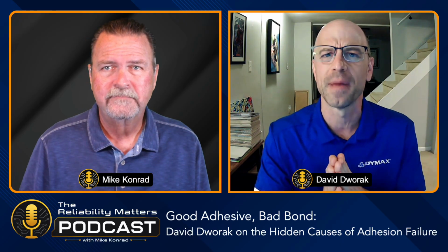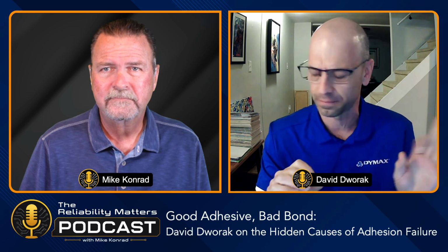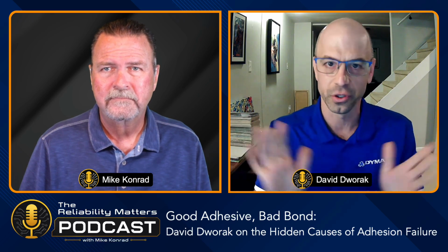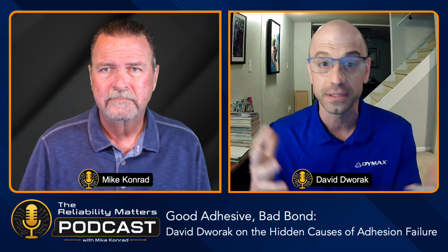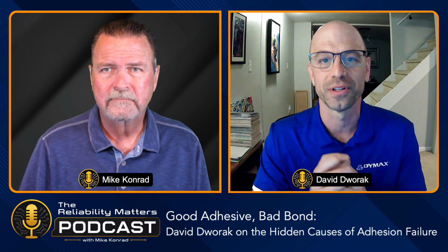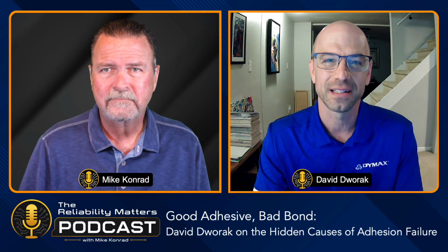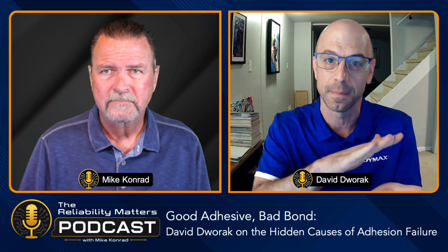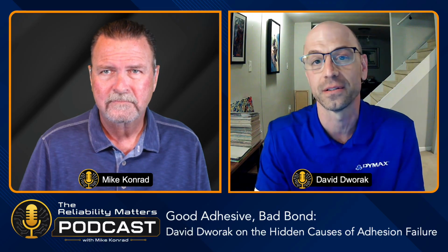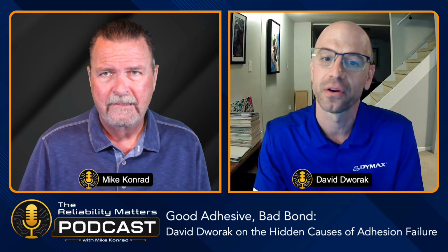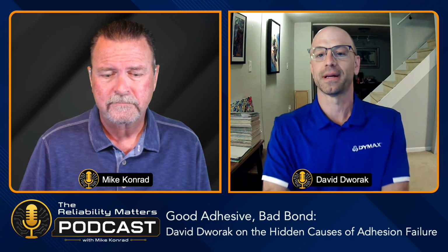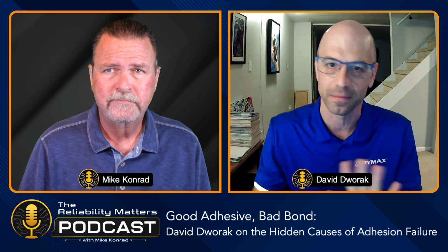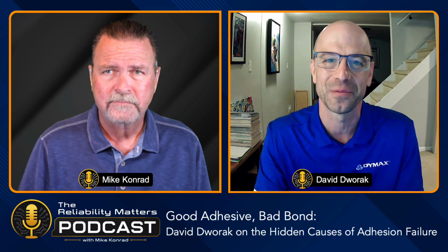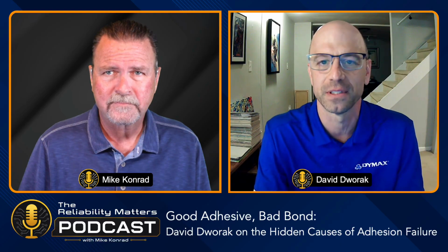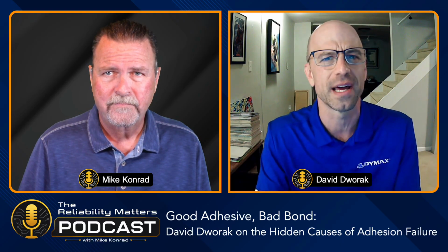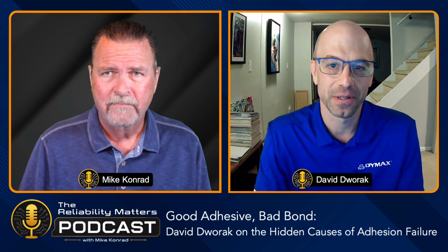But let's even take metals. Let's say you polished and cleaned your aluminum to a perfect shine, and you're good. But you let it sit for several days before bonding. Well, this gives the aluminum time to react with the moisture in the air and form an oxide layer, and those oxide layers sometimes don't adhere very well to the base metal itself. So now you're bonding to an oxide layer and not the metal. So cleaning is a very important step in surface prep. But surface energy, contaminants, surface chemistry, all that stuff needs to be considered. Again, it's an assumption that we talked about earlier where the surface is fine. You just got it in, cut the box open, use as received. It might not be as clean as you think.